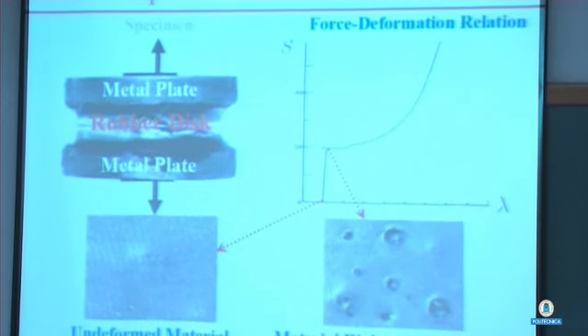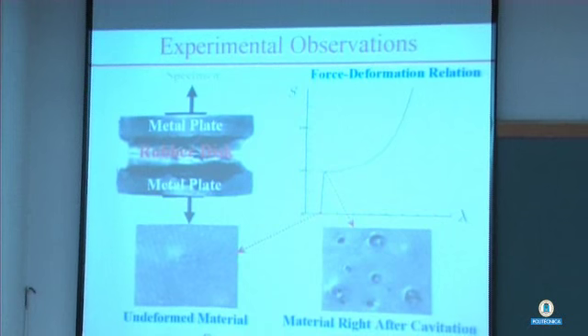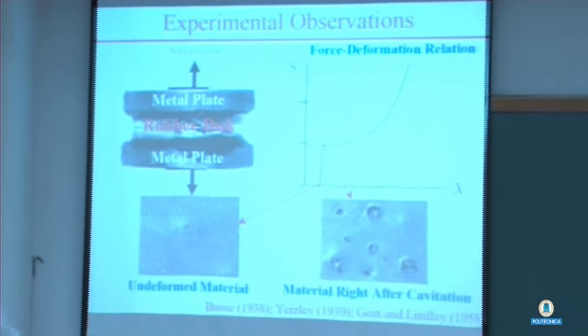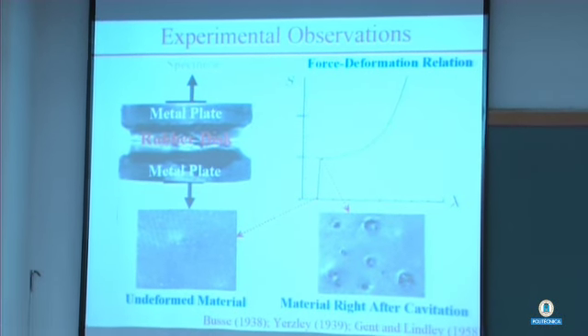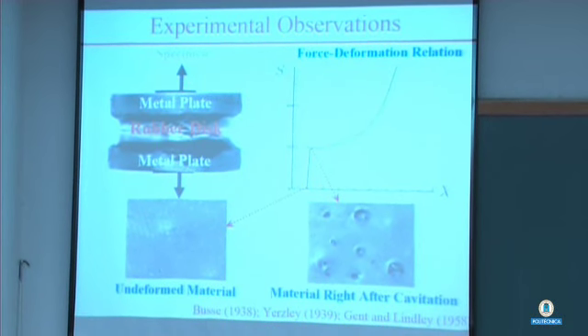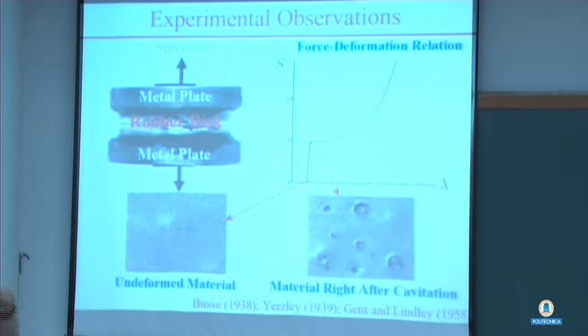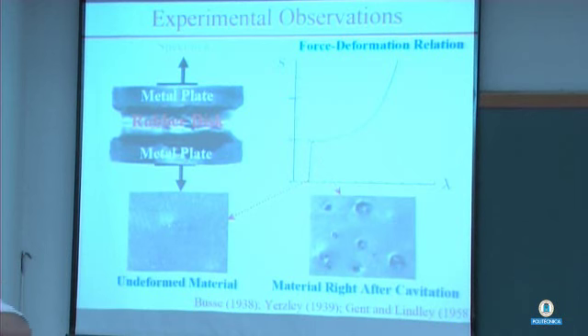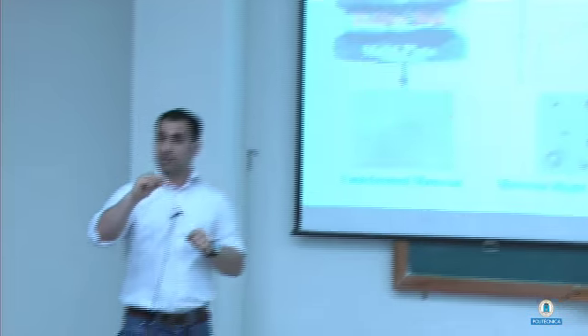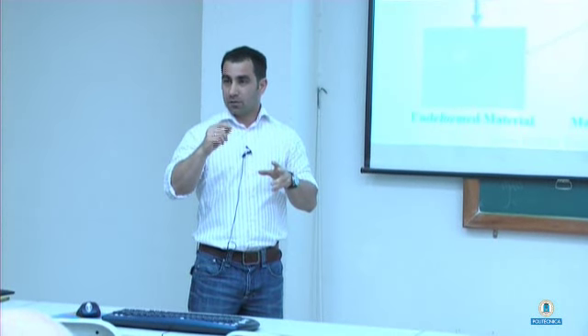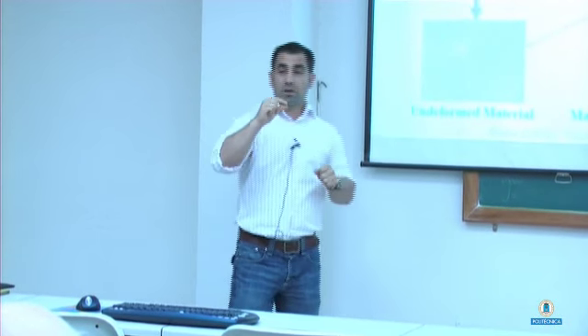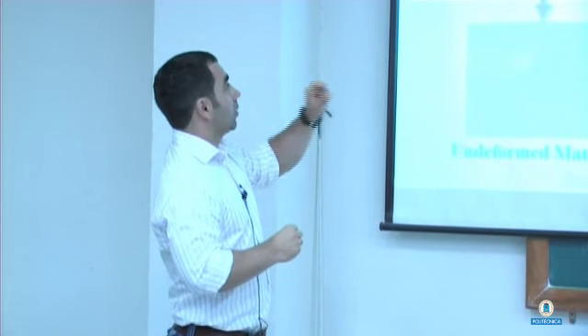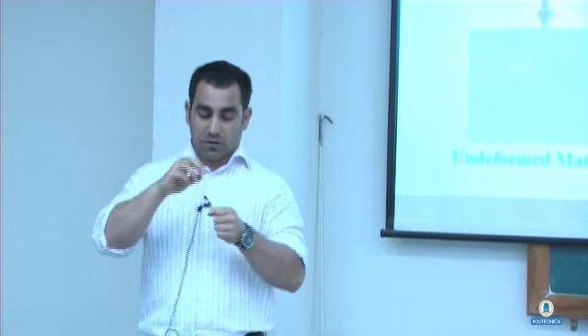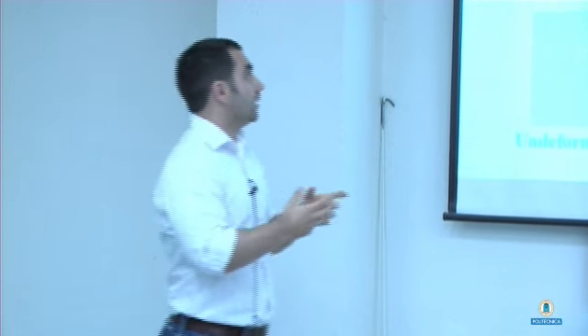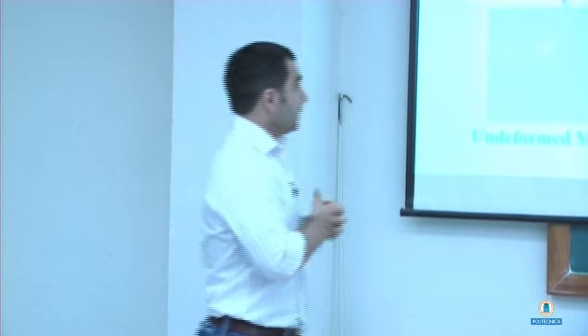In the 1930s, people were doing a lot of experiments on rubber because the automotive industry started to use it very heavily. One of the experiments, and the one I'm showing here belongs to Gent and Lindley, in the famous 1958 paper, is putting a thin disc of rubber glued to metal plates and applying tension to this structure. Because the disc is glued to the plates, the state of stress and strain in the rubber is not homogeneous, it's heterogeneous. If you make the rubber disc very thin, you can accomplish a huge hydrostatic pressure in the center of the specimen. So this is a cheap way to apply hydrostatic pressure in rubber.